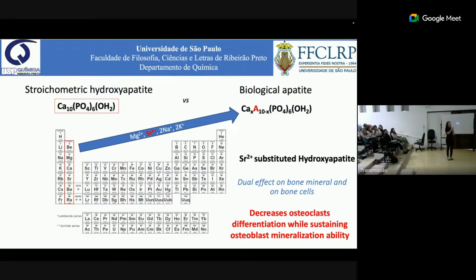I'm joking, but because calcium and strontium share the same family in the periodic table of elements, they have similar chemistry. When we drink mineral water, if you look at the ingredients, you see that we take in strontium daily in our diet. And due to the similarity with calcium, strontium attaches mainly to our hard tissues. But what is important in this kind of substitution? That strontium can have a dual effect in controlling bone cells, the cells responsible for bone formation and for bone resorption. And we can take advantage of this effect.